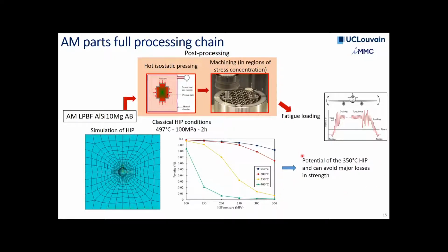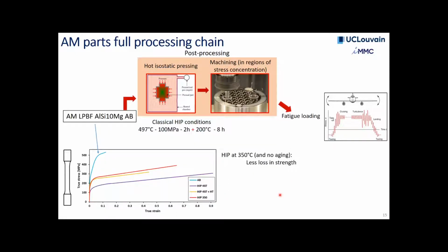So we wanted to test the potential of this 350 degrees hot isostatic pressing condition to avoid the major losses in strength that you can observe with the 497 degrees, and I'm just going to show you in the next slide. So we've been trying this 350 degrees. And the advantage with these 350 degrees is that you don't have this additional 200 degrees heat treatment, which is a two-step heat treatment in the hot isostatic pressing. And so here is what the tensile properties look like.